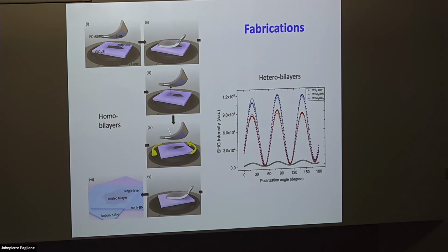So the difference is only in this step, you cannot just rotate an angle. You have to do this extra step here, sorry, to characterize the crystal orientation. And an additional nice thing coming out from this second harmonic generation technique is that there are 2 different ways to stack this heterobilayer on top of each other. Because each of the monolayers is only 3-fold rotation symmetric, there's a difference. You stack them at 0 degree or 180 degree, they are different.